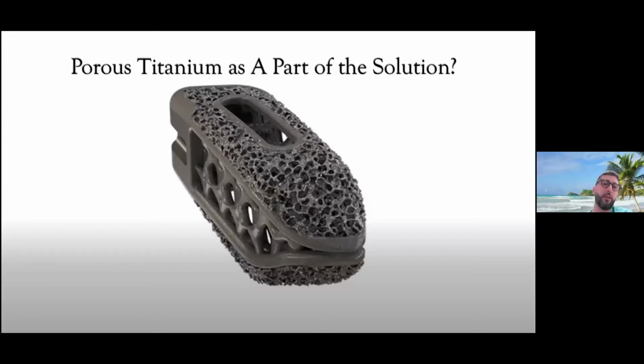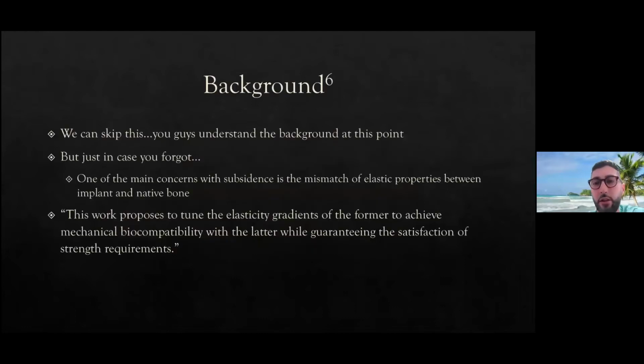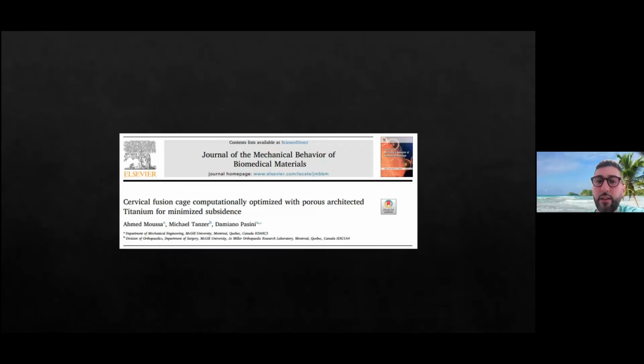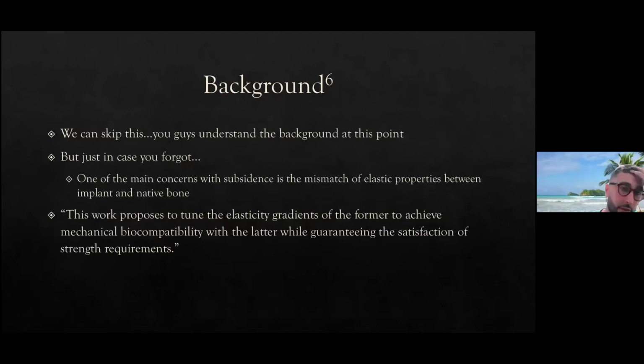And so, a lot of you are familiar with these porous titanium grafts. They're becoming increasingly prevalent. And the question is, why are they becoming increasingly prevalent? And do they potentially deal with this issue of mismatched modulus of elasticity? So this is a study that was done in the Journal of Mechanical Behavior of Biomedical Materials. And it's kind of a complicated study. If you really want to understand this very well, I recommend you book Ian Cahigas for an hour. But you guys understand the background of why they're doing the study. They're trying to see if you can architect a titanium graft to more closely match the modulus of elasticity of the bone.